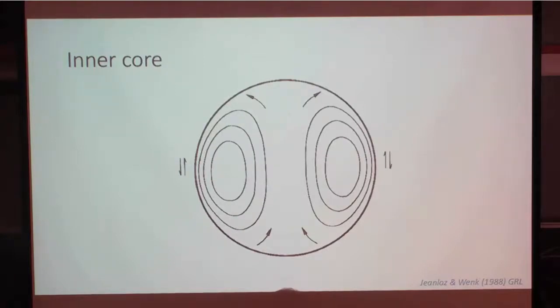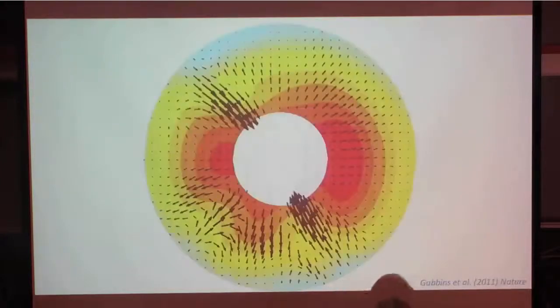Although the inner core might still be interesting, that doesn't necessarily mean that it's static. This is one proposal that was made recently by Dave Gubbins, based on looking at lateral variations in heat flow at the core mantle boundary, which can be very, very large, 100%. And you might even get downwelling regions and upwelling regions in the outer core. And these may cause lateral variations in the growth rate of the inner core, which could cause internal mass rearrangements. So there might be interesting things going on in the inner core, but it's probably not the sort of standard thermal convection that we usually think about. I'll stop there. Thanks.